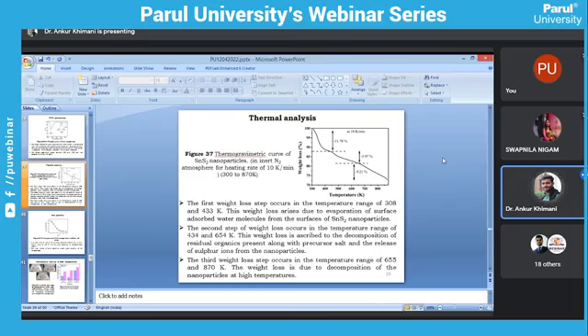The second step of weight loss occurs in the temperature range of 434 to 654 Kelvin. This weight loss is ascribed to the decomposition of the residual organics present along with the precursor salt and the release of sulfur ions from the nanoparticle. The third weight loss step occurs in the temperature range 655 to 870 Kelvin. The weight loss is due to decomposition of the nanoparticle at higher temperature. So as the temperature increases, different characters of the sample are seen.